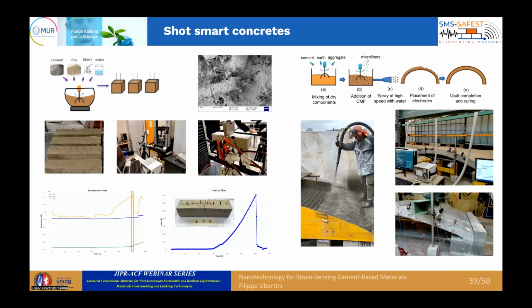So this was the result of a large project that we ended recently. In this project, we were investigating earth cement materials. So materials where 2/3 of the cement is substituted by raw earth to obtain sustainable material. But then we added carbon microfibers to improve a little bit the tensile behavior, but mostly to obtain strain sensing capabilities.